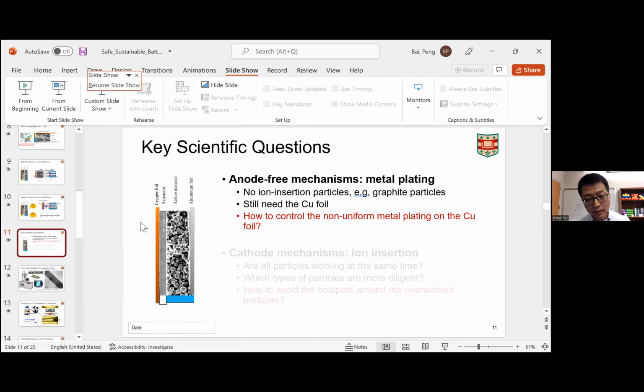When you charge the battery, ions, you are right, for whoever asked the question, ions will move toward the cathode and toward the aluminum foil. But the problem is that you are not at the right potential to do this. So the condition does not allow metal plating. Metal plating only happens when you have a lower potential, where you can receive the electrons. And for the aluminum foil on the cathode side, you don't have to worry about the lithium metal or sodium metal growth.